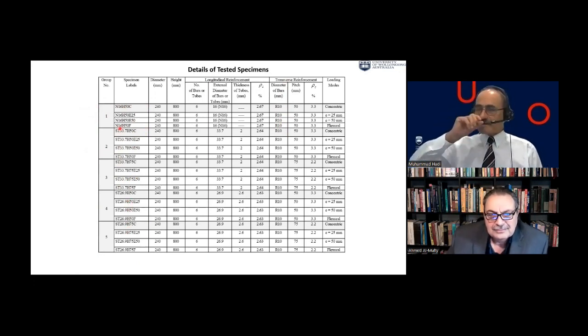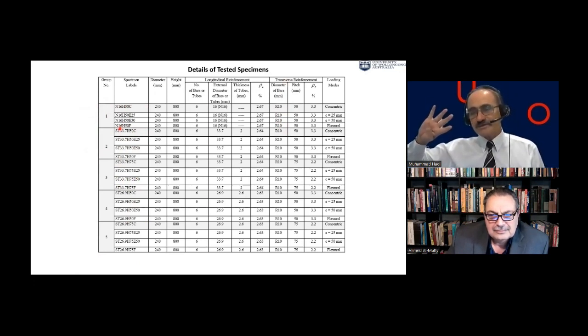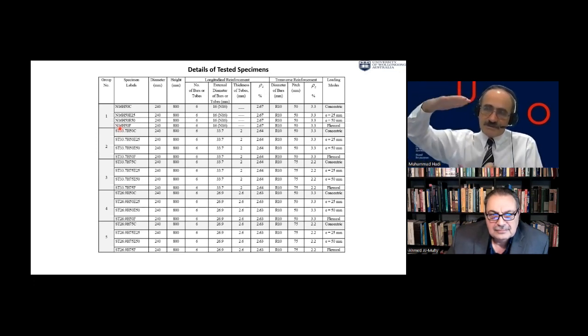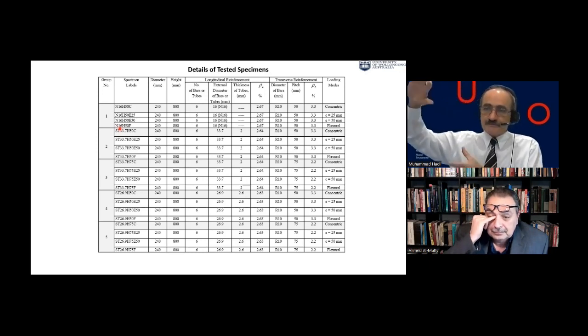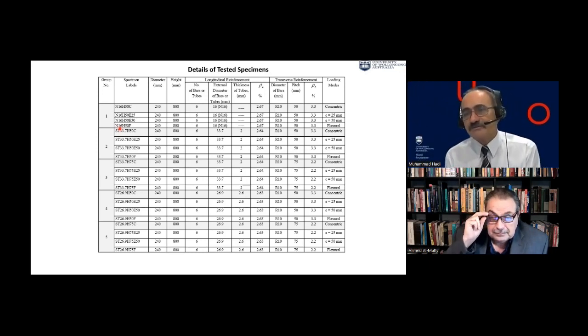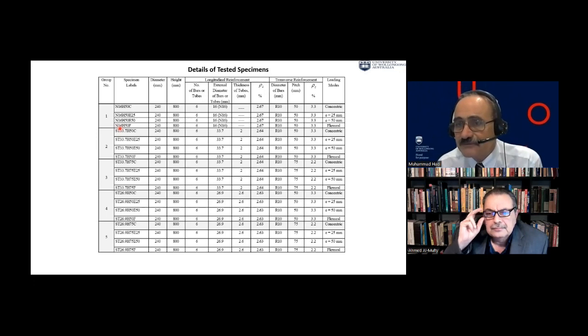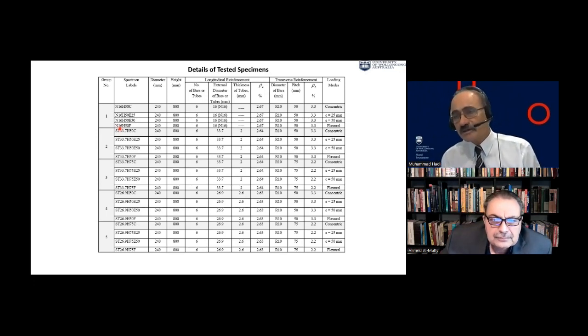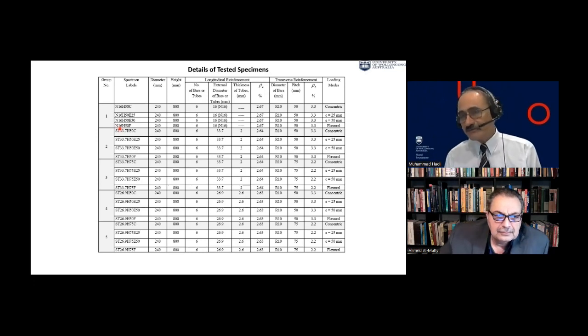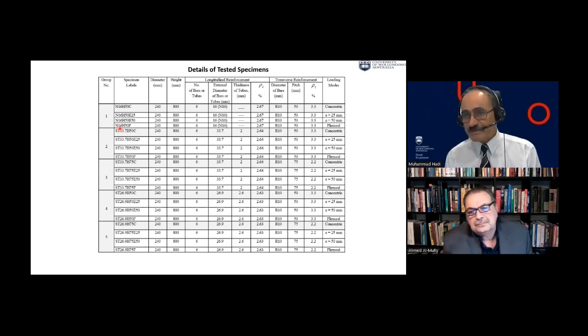Now, each group of specimens has 4 specimens. The first specimen, we tested as a concentric load. The second one under 25 millimeter eccentricity. The third one, 50 millimeter eccentricity. The last one was flexural, 4-point bending. So you can see we have 5 times 4, 20 specimens.